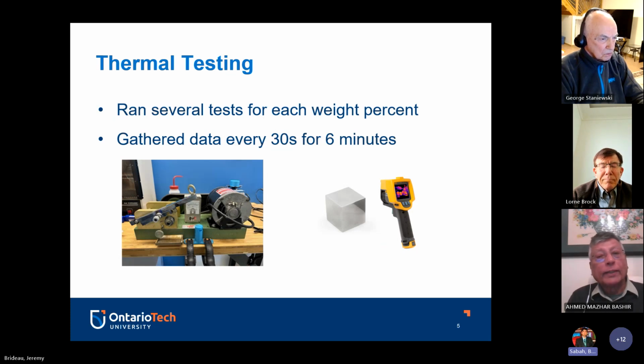Every 30 seconds, we take a photo with the TI-32 Fluke camera. It's a thermal camera that is used in many OPG reactor teams. We would take these thermal measurements every 30 seconds for 6 minutes. We chose 6 minutes because at that point our machine got extremely hot and it wasn't producing desirable results, or it would just mesh everything together after that.